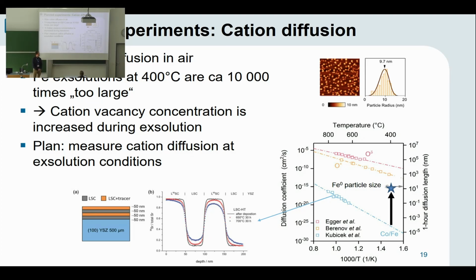One thing that came to my mind: in principle, you can circumvent the bulk diffusion by having a lot of mobility of steps at the surface, because surface diffusion is many orders of magnitude faster than bulk diffusion. But did you do AFM and look whether you see voids or depressions in the surface? So I think the surface roughness does not increase that dramatically during the exsolution process. There are even reports where exsolutions are happening and step terraces are still visible on the rest of the oxide. So it seems to be a very localized phenomenon where defects accumulate and an exsolution appears.